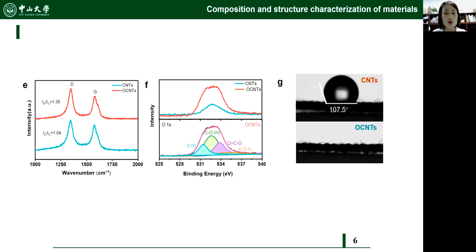The intensity ratio of D-band and G-band in Raman spectra rises from 1.04 to 1.35, indicating the increase of surface disorder caused by oxygen introduction. From the oxygen 1s spectrum, we can see that the electrochemical oxidation of CNTs results in an increase of total oxygen content with the formation of oxygen functional groups. Also, the introduced oxygen groups improve the surface wettability of OCNTs. The surface of OCNTs is super hydrophilic compared with CNTs.